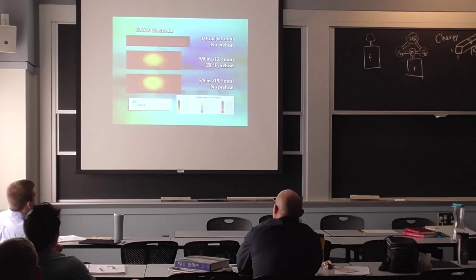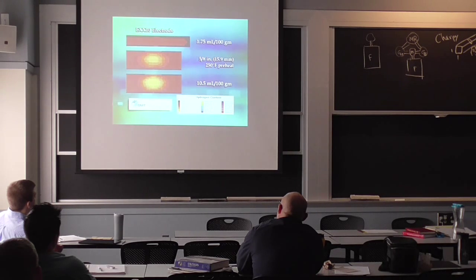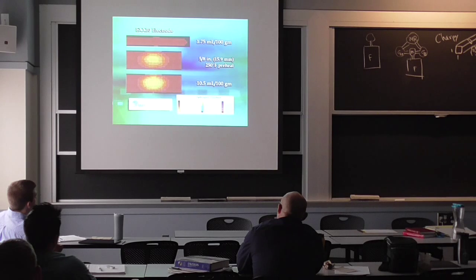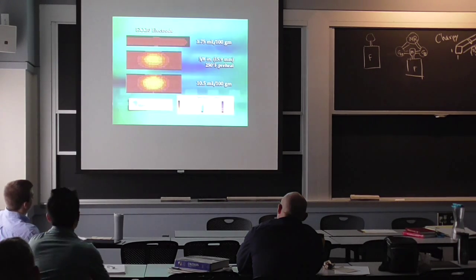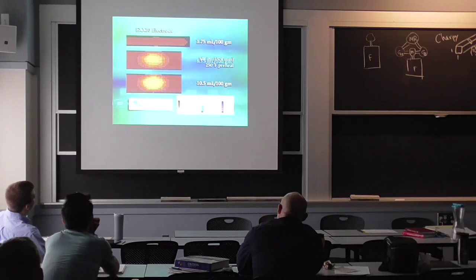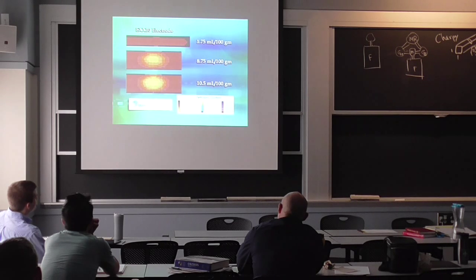The maximum hydrogen levels present 3 days after welding are 1.75 milliliters per 100 grams for the 1/4 inch thick pipe and 10.5 milliliters per 100 grams for the 5/8 inch thick pipe. The 250 degree preheat for the thick wall pipe allowed more hydrogen to diffuse away and lowered the maximum remaining hydrogen level to 8.75 milliliters per 100 grams. Post-heating following the completion of welding can further reduce weld hydrogen levels.